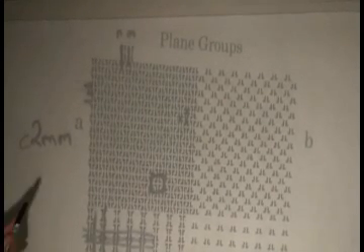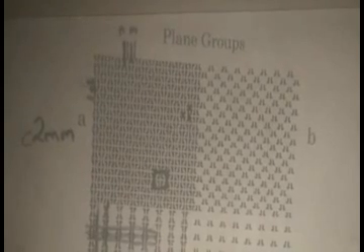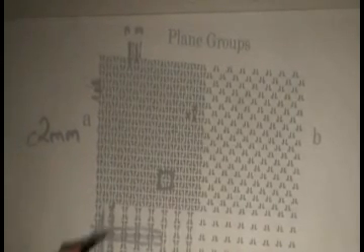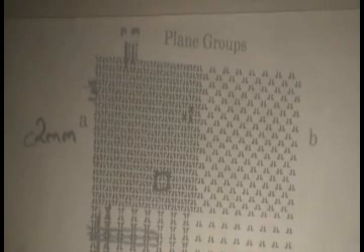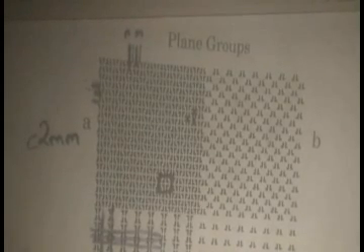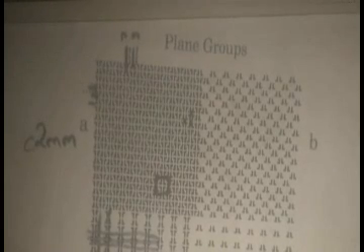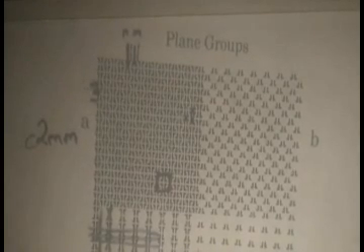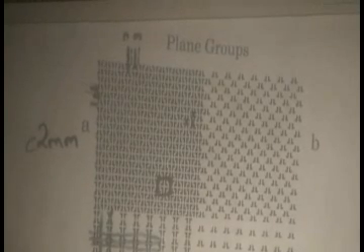So an object at x, y also appears at x plus 1/2, y plus 1/2. If it was sitting right on the corner, that 2-fold also appears in the center, sure. But it works for anything. It doesn't have to sit at 0, 0. So that's C2MM, glides in 2 directions, and therefore systematic absences, as you saw on the little thing, in both directions. Okay.